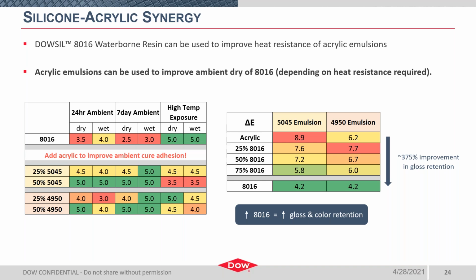Okay, so we know that 8016 can improve post-heat, wet and dry adhesion, and color and gloss retention of waterborne acrylics. But I want to look at the data from a different perspective. Let's say we're formulating with 8016 resin, and while the post-heat adhesion performance is excellent, we know less than optimal ambient dry adhesion, whether that be the 24-hour or 7-day.